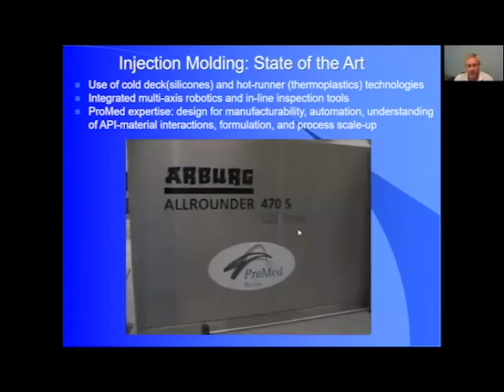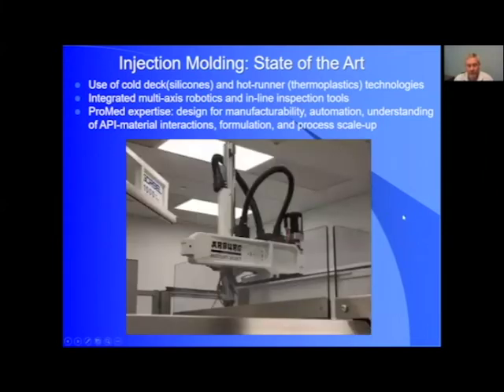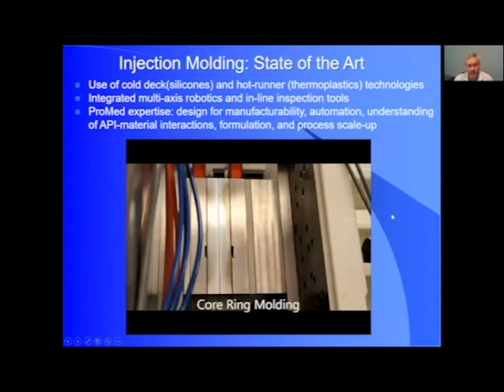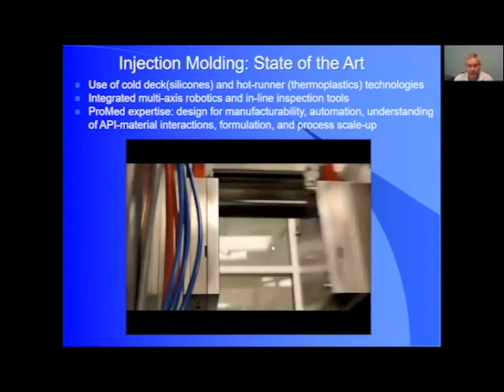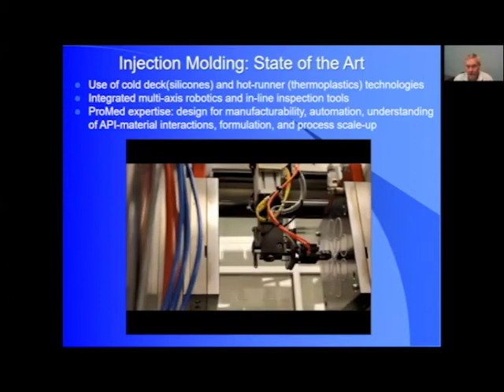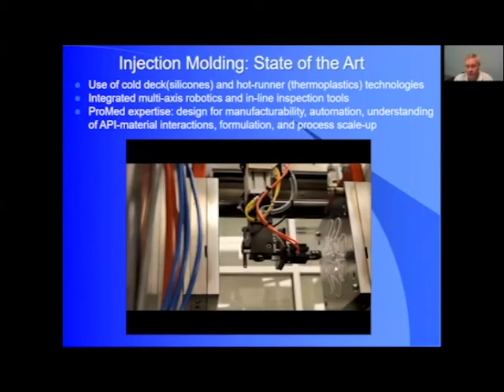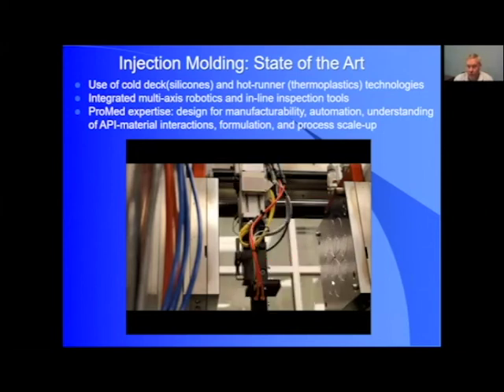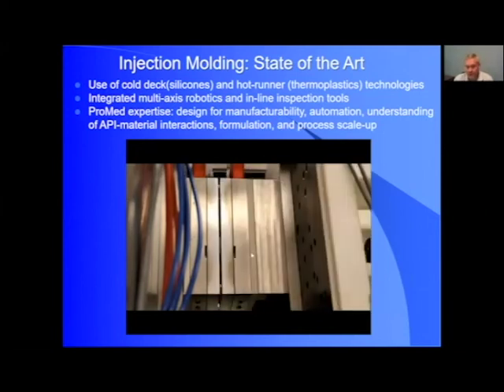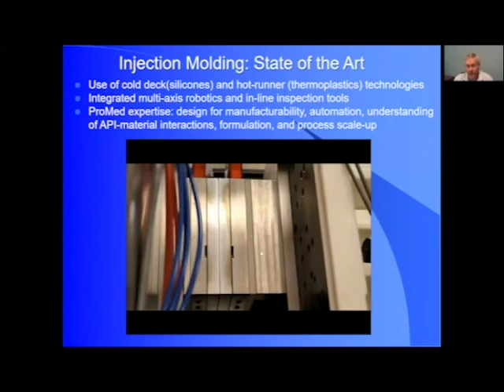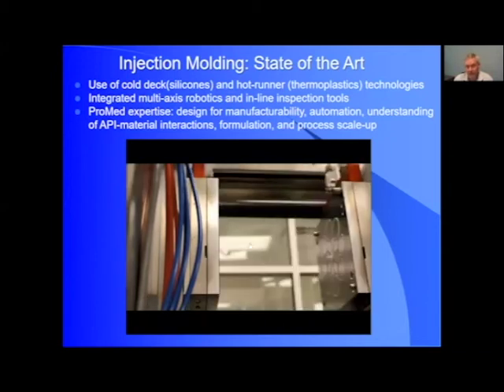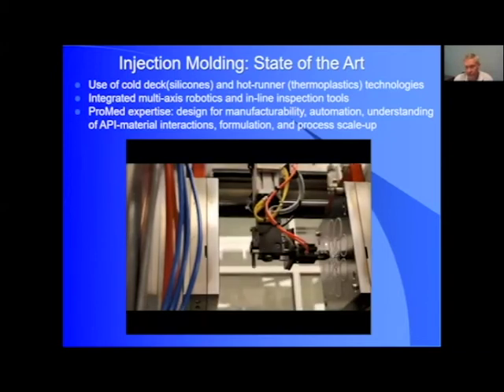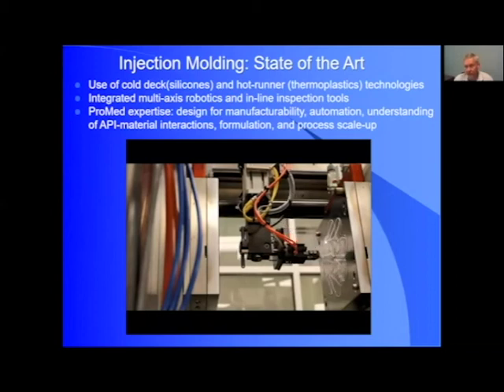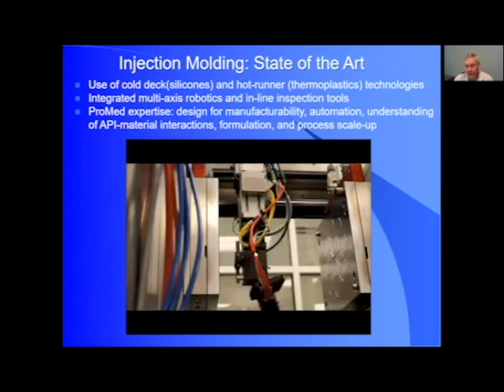So hopefully I can run this and show you an example of an injection molding press in operation. Again, this is the state of the art for us. And so you see here the ring mold and a robot coming in, and this is silicone, a number of silicone rings that are being molded all together. So basically you have a center feed, gates that come out and form these drug-containing rings. And so basically, we can just break off the runner from the ring and have a finished component.